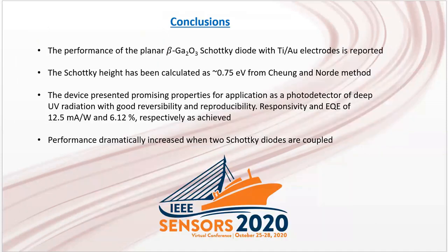Just some conclusions: the performance of planar gallium oxide Schottky diodes is reported. We've measured the Schottky barrier height of around 0.75 electron volts, but one of the main achievements is the fact that the performance has dramatically increased when we are able to couple two Schottky diodes together. Thank you.